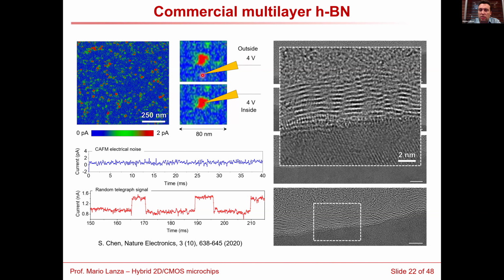at the insulating location and inside one of these conductive spots. For the same voltage, in one of these insulating locations, we just observe electrical noise. However, when we put the tip in one of these electrically weaker locations, we observe that the currents for the same voltage are much higher, and we also observe random transitions between two levels.